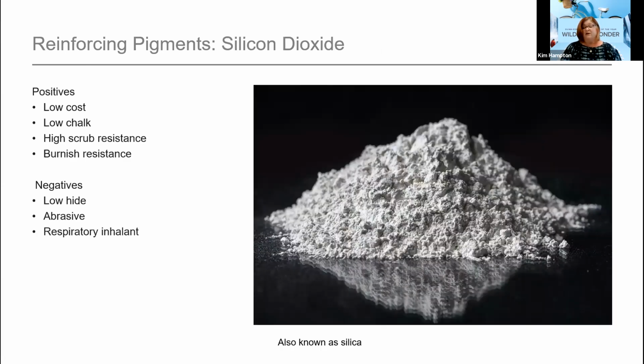Reinforcing pigments, silicon dioxide. The positives here would be low cost, low chalk, high scrub resistance, and burnish resistance. The negatives would be they are low hide, they can be abrasive, and it's also a respiratory inhalant.